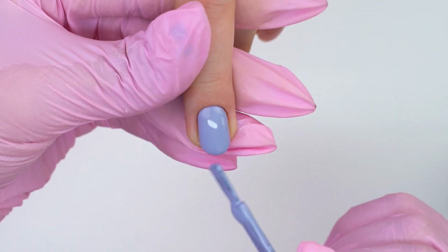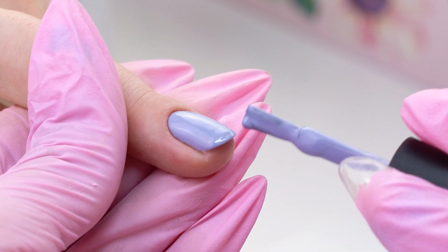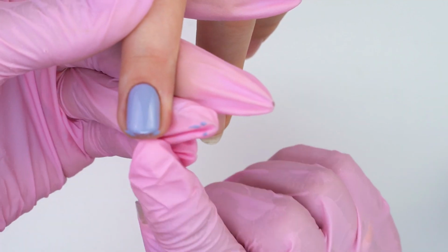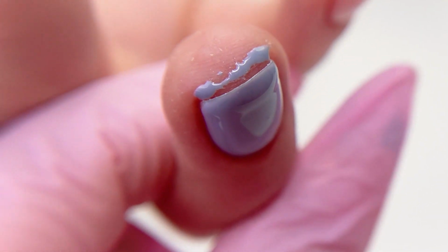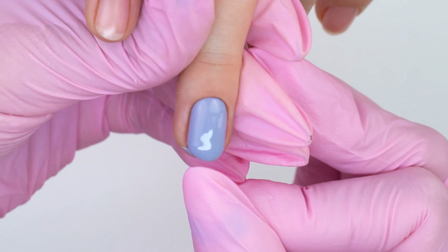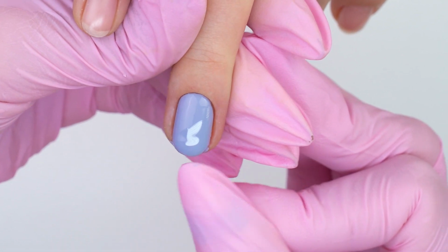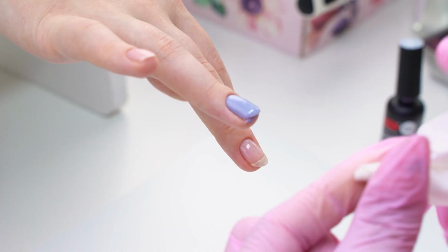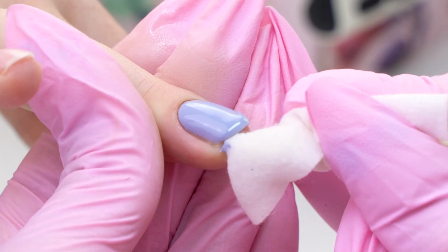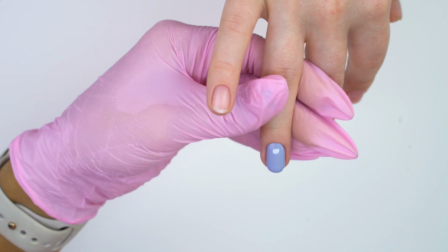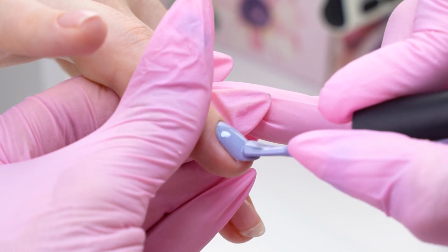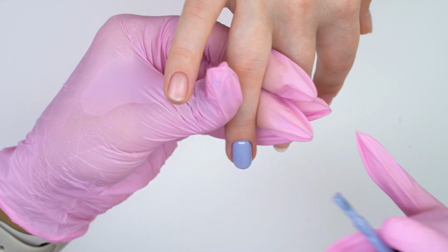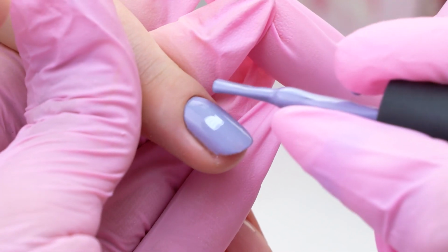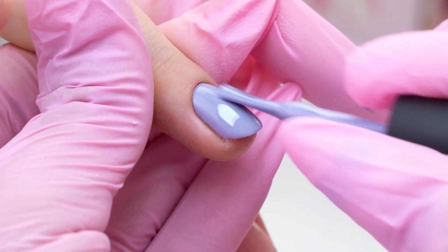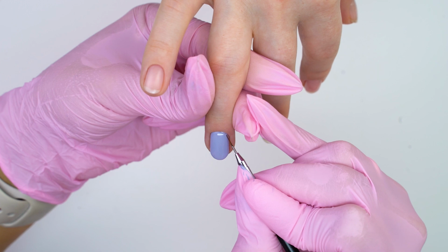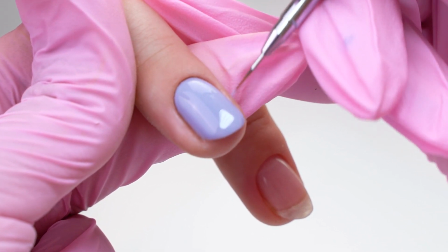Some nail techs often place the brush like this and start moving from side to side, sealing the free edge. Getting it on the skin and messing it up, and getting the material under the nail plate. Then when the water gets there, the coating will lift up, and so will the base coat. If it still happens, make sure to remove all the slicks using a tissue soaked in a dehydrator. Remove all the extra material from the free edge and make only long moves from the cuticle to the free edge. Lay the brush down. Then the coating will get spread evenly. Or pull it to the center with a thin brush.